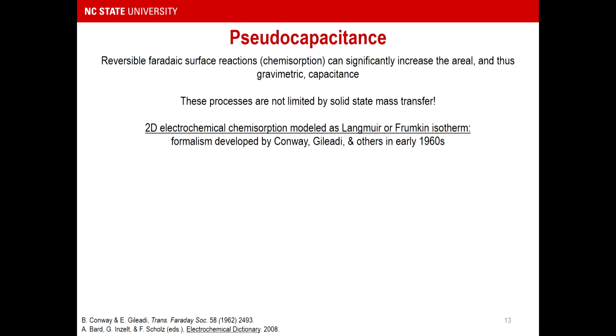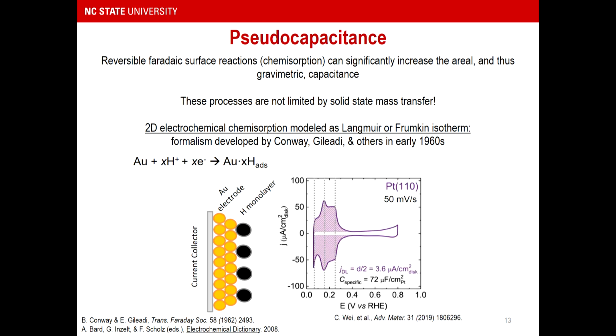And where this developed was in the early 1960s by considering electrochemical adsorption processes at surfaces as Langmuir or Frumkin isotherms, formalisms developed by Conway, as well as others. And so the idea is that if you have something like a gold electrode and you have the adsorption of hydrogen on the surface, this process right here, nominally your cyclic voltammogram begins to look like this. And you have what's typically assumed to be the double layer contribution here highlighted in white, but then you also have these Faradaic peaks that are incredibly symmetric, giving rise to a mirror image cyclic voltammogram. And those are associated with this chemisorption process.